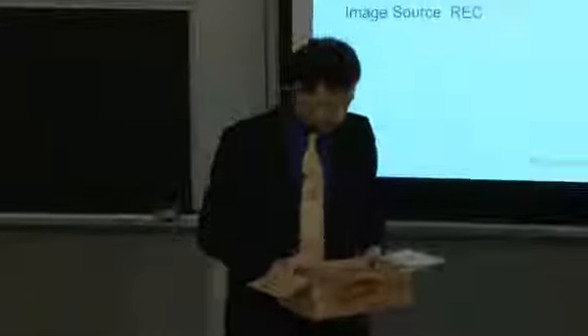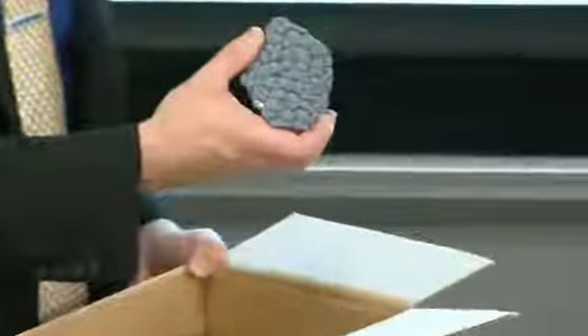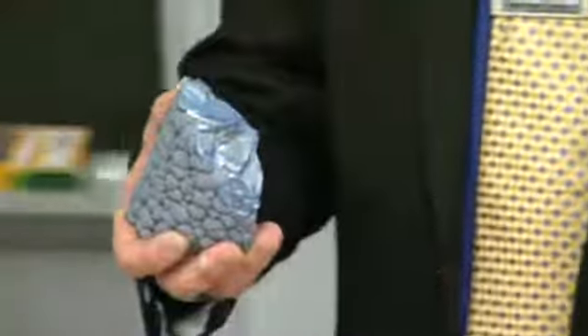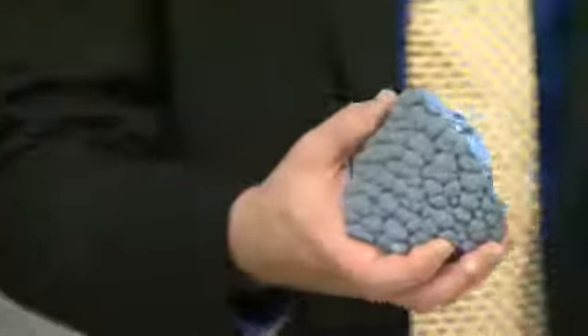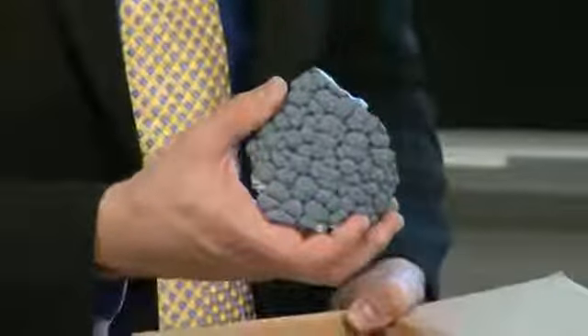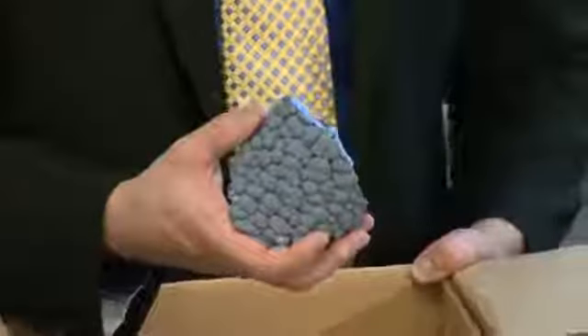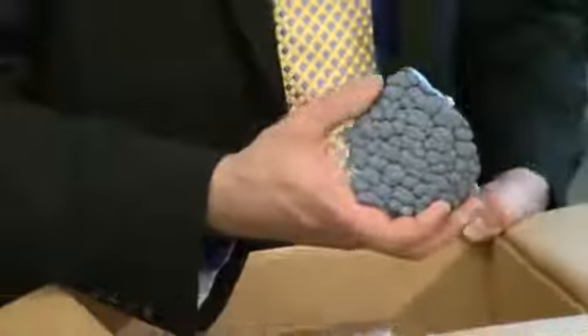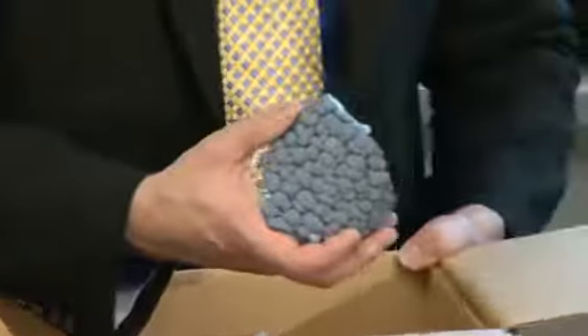So what I'm going to do is pass around an example of a chunk coming from this Siemens rod. Be very gentle with it, please. On the outside, you can see a corrugated, rough, cauliflower-like structure. That's because you're optimizing for deposition speed, not for beauty of the surface. You don't really care how flat it is, unless you're trying to grow a very specific type of material called float zone, which we'll get to in a second.